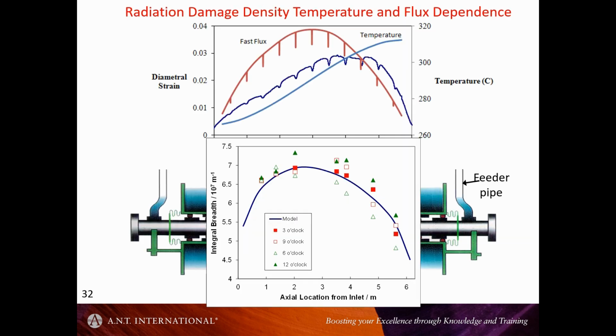So this is back to front, but what I wanted to show is the loop damage, this is the A-type loop damage now, in a Zr-2.5Nb pressure tube. The density of the damage varies according to the temperature and the flux profile. So we tend to have a distribution of damage along the length of a 6-meter long tube, going from the inlet here, I'll get the pointer again, going from the inlet here to the outlet here.